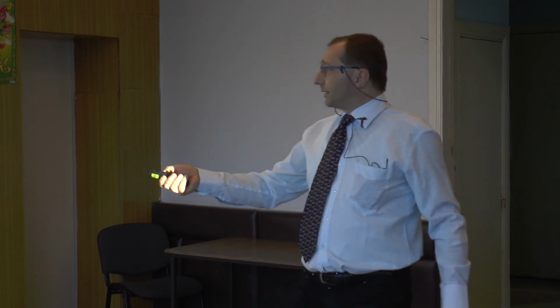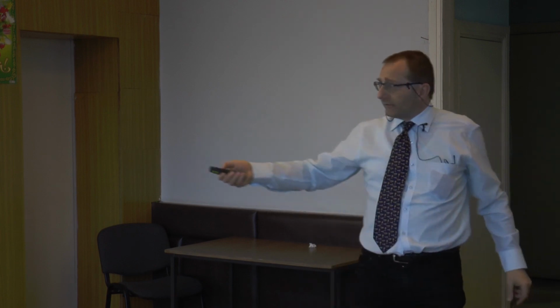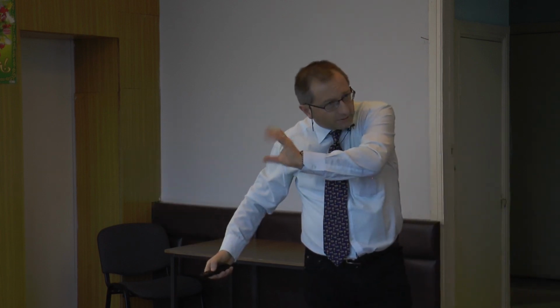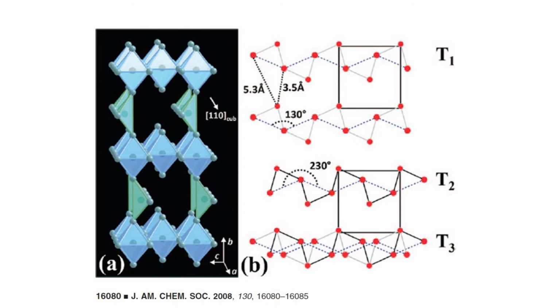If this would be the case, this is not, but if this would be the case, you see that these ordered systems create a channel here. And through this channel there is room enough for oxygen to migrate, right? The point is that in reality the situation is not like this, because these tetrahedra are randomly oriented. This means that if, for instance, one of these tetrahedra flips into this direction, it will close the door. And the oxygen conduction will be no more possible, right?